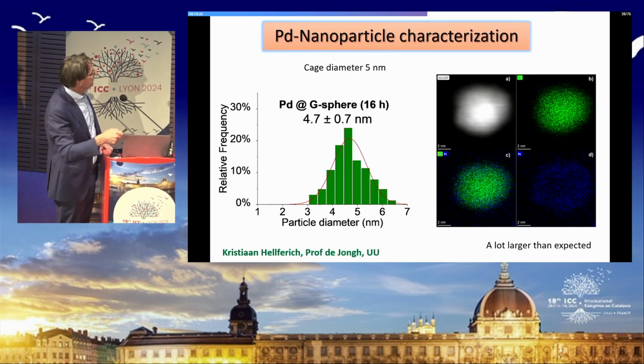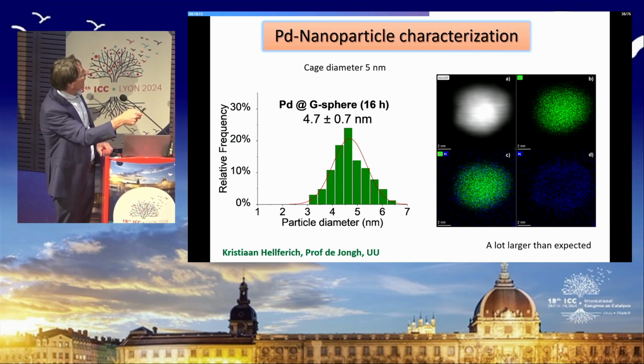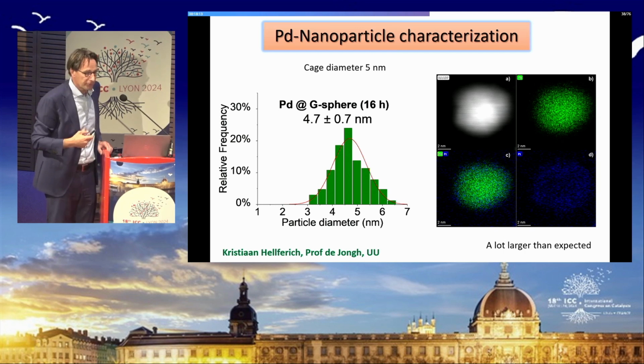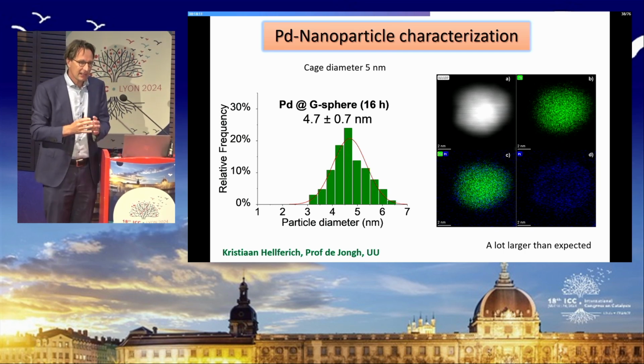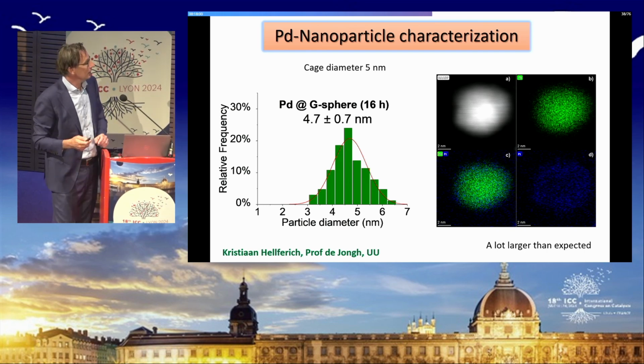Next, we did the analysis in collaboration with the group of Prof. de Jongh, and now we find much larger nanoparticles. Here you can see up to 4.7 nanometer, whereas the cage diameter is about 5 nanometer. And this indicates that for palladium, apparently the whole cage is filled with nanoparticle, and further growth is just prohibited by the boundaries set by the cage.